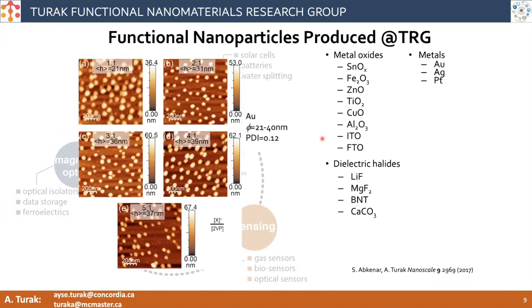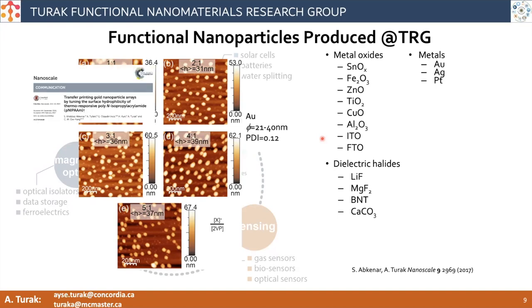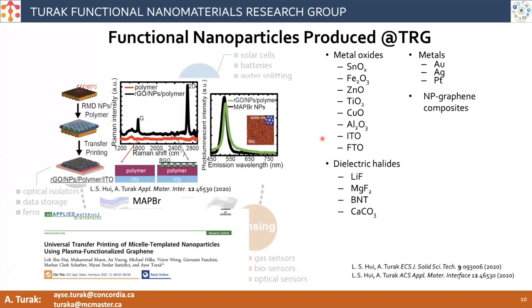We've also made different kinds of metals. And in fact, we're not the only group in the world that does this, and this is the most common approach usually. When people use diblock copolymer micelle synthesis, they're often targeting things like gold and platinum. But we also do that. We've made different nanoparticle graphene composites, right? Because it's possible to graft these nanoparticles onto things like graphene or other types of structures, both in solution and once you deposit them on the surface.